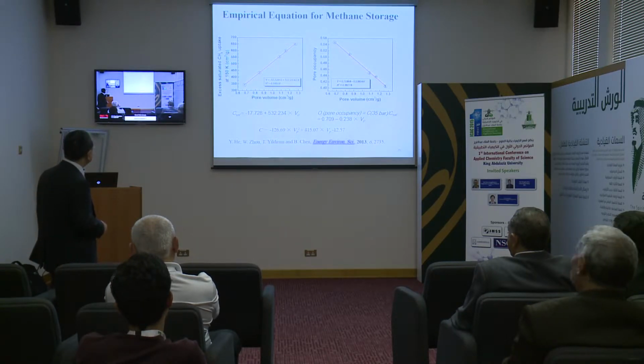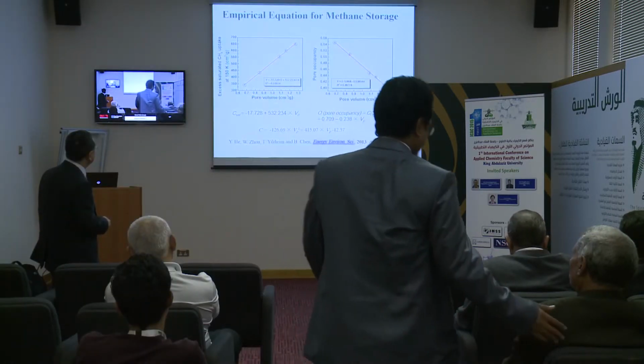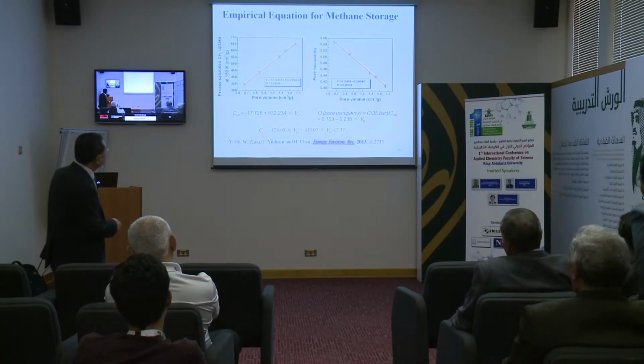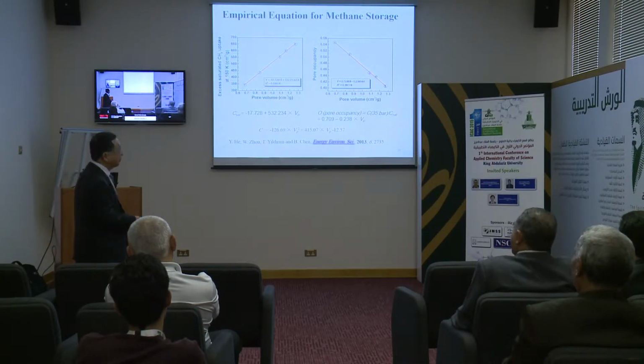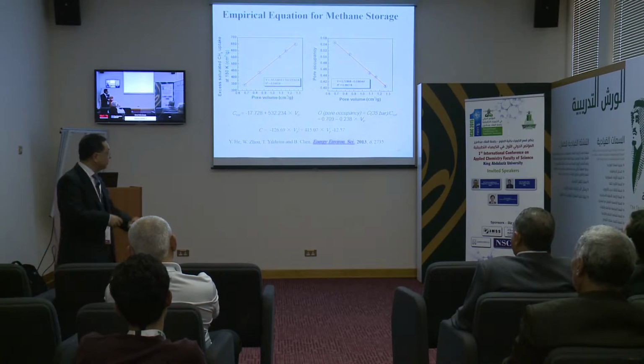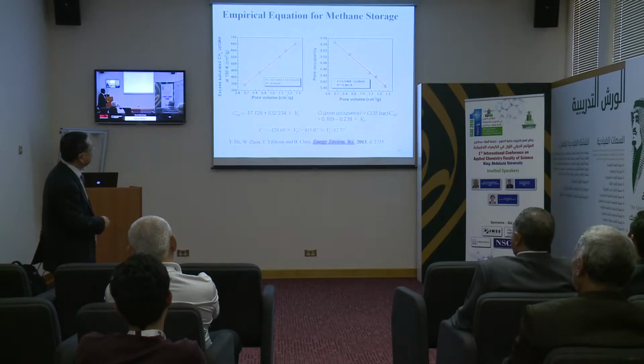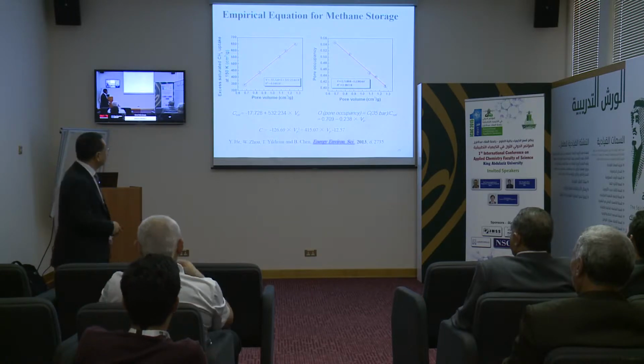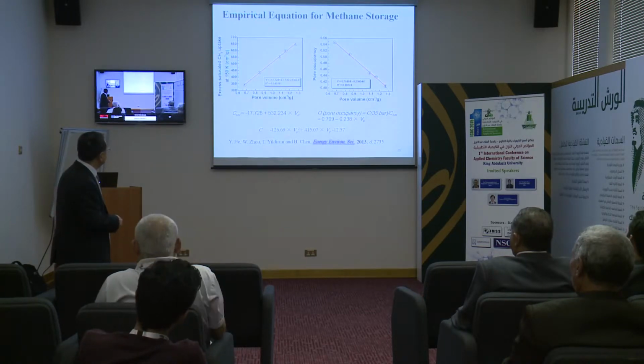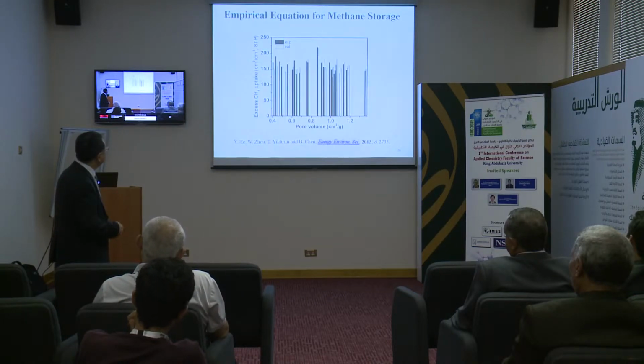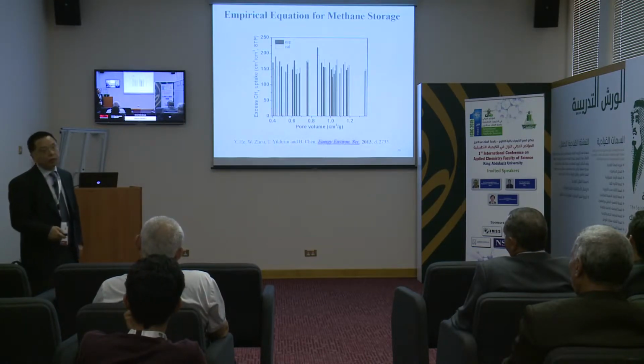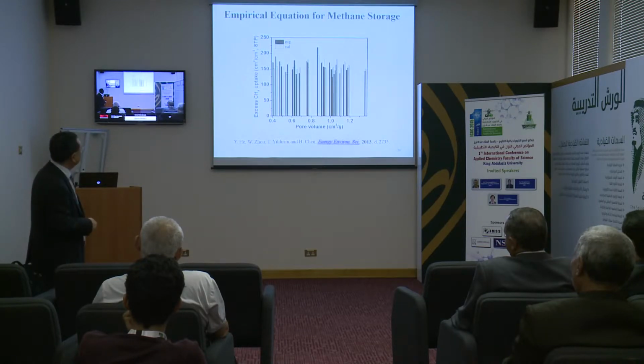So basically here is the saturated one. Basically the saturated one is proportional to the pore volume, while the pore occupancy is defined as the storage amount at these storage conditions divided by the saturated one. So this pore occupancy is inversely proportional to pore volume. It is understandable: the larger the porosity, the less the pore occupancy. So based on this equation, we can figure out this empirical formula. It turns out that it matches the experimental one quite well, within around 10%, which I think is quite good.